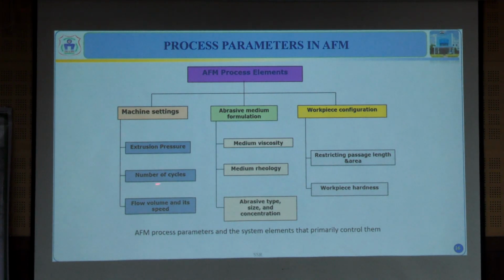Second is the number of cycles. When we pump the media from one cylinder to another cylinder, we calculate it as one cycle. So when the media is pumped from the bottom cylinder to the top cylinder and then from the top to the bottom again, we calculate it as one cycle. If you increase the number of cycles, the surface finish will increase, and the material removal will also increase. So this is also one of the important parameters.